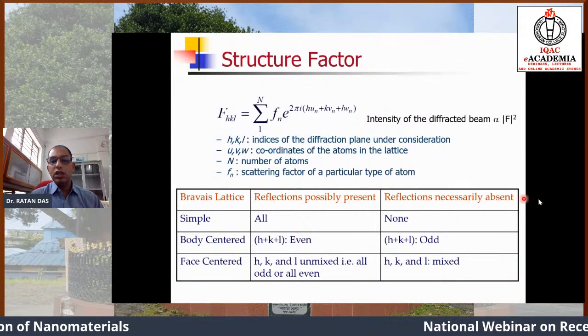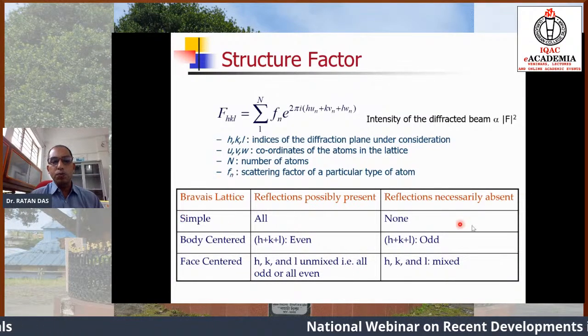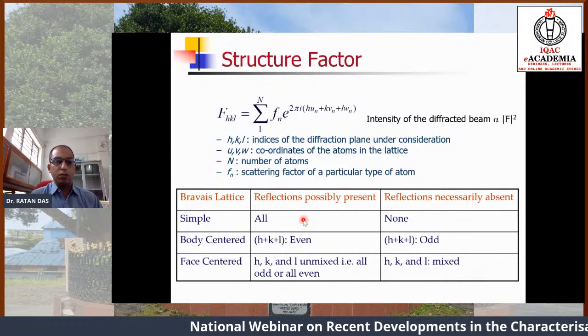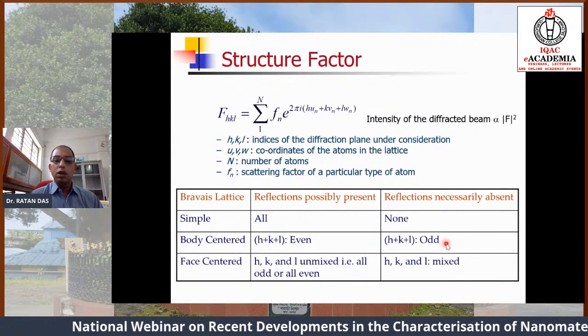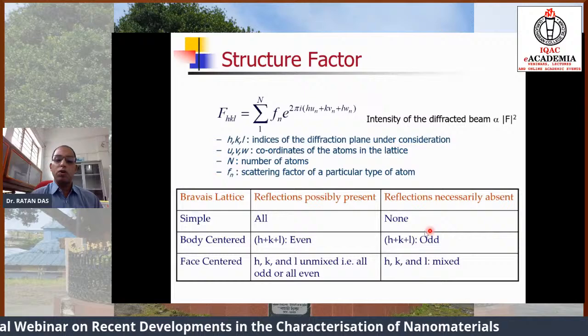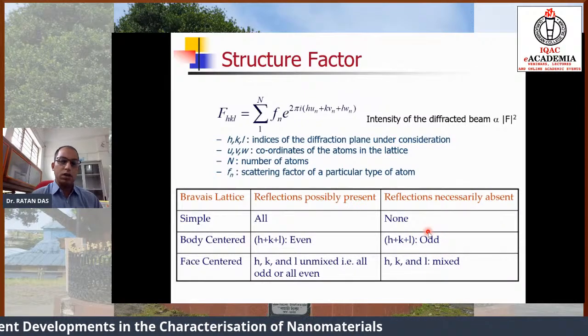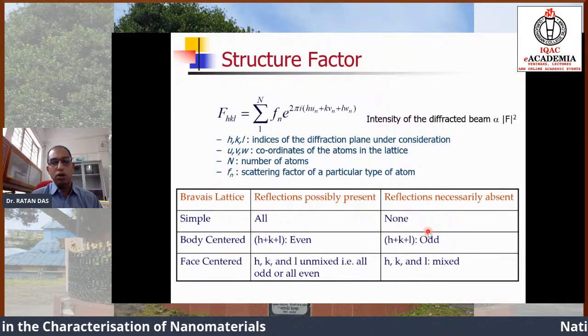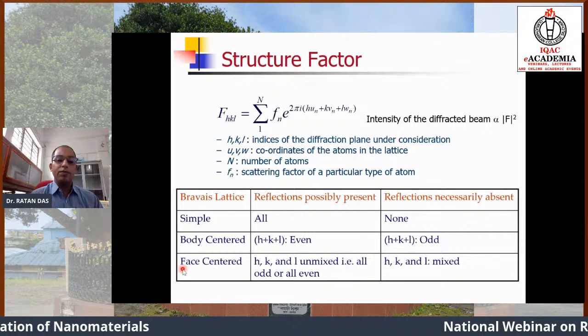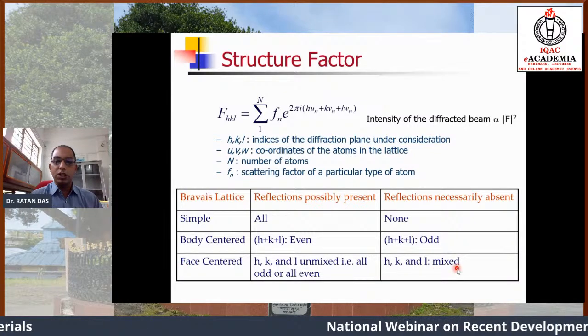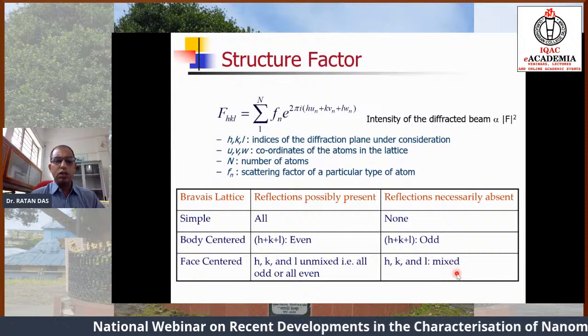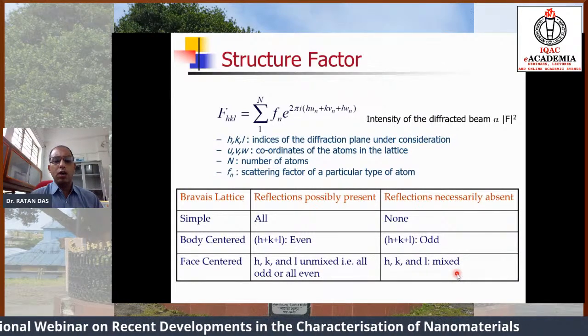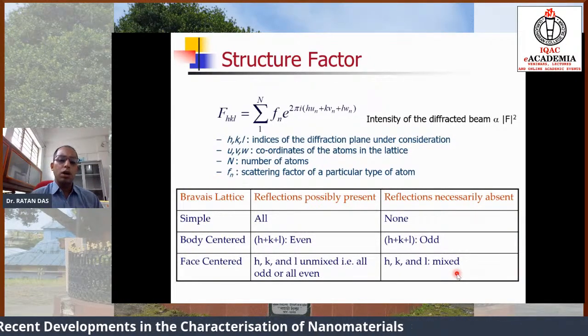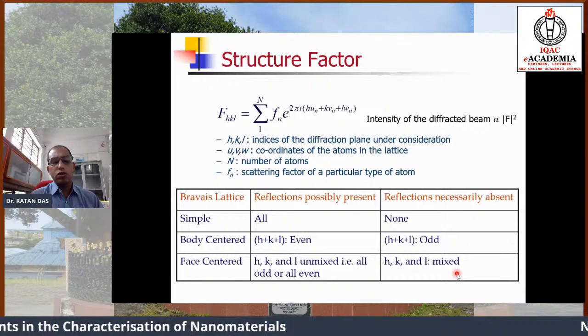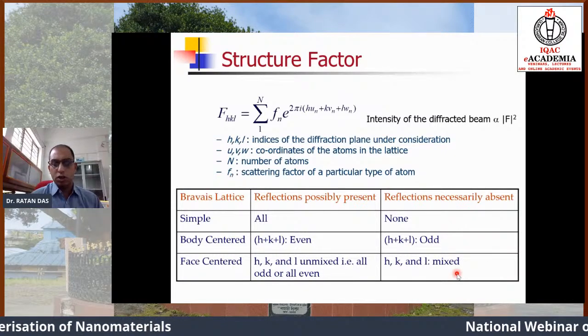So reflection necessarily absent in the case of simple is none, all are available. In the case of body center, where the HKL sum becomes odd, these are absent. And in face center, where HKL are mixed, odd and even, this is not possible. So these simple things you have to know in the analysis of the X-ray diffraction data.